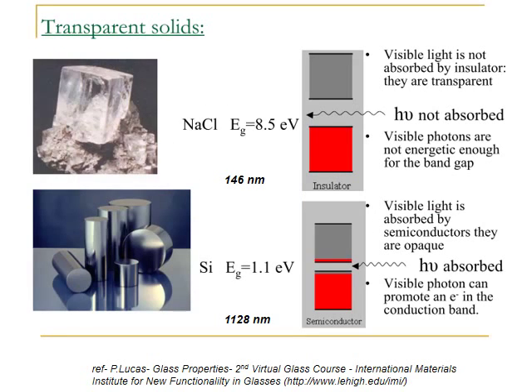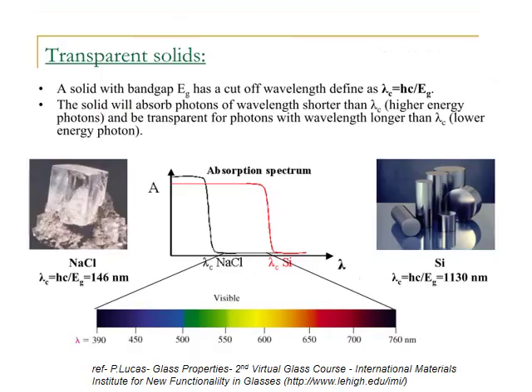But let's come back to the transparency window of solids. Sodium chloride is completely transparent in the visible. The energy gap is 8.5 eV, or 146 nanometers. Silicon is black. It absorbs visible light. The energy gap is 1.1 eV, or 1128 nanometers. It's a semiconducting material, the base for our photovoltaic cells. These are the absorption spectra for these two materials.